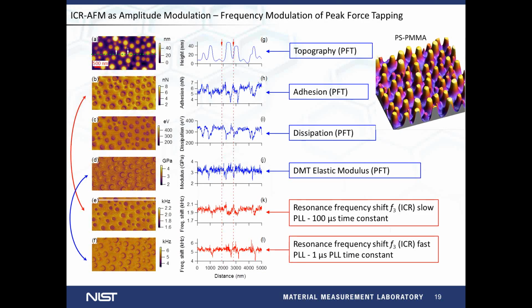And here is an example of such measurements. We have maps acquired with regular PeakForce Tapping: topography, adhesion, dissipation, and modulus. This was done on a polystyrene-PMMA blend. The polystyrene was the matrix, and the PMMA the cylindrical pillars here. The last two maps are the resonance frequency acquired with PLL, either with a slow PLL or with a fast PLL. Just by looking at the color contrast, we see a correlation between the slow PLL map and the adhesion one, and the fast PLL map and the modulus one.